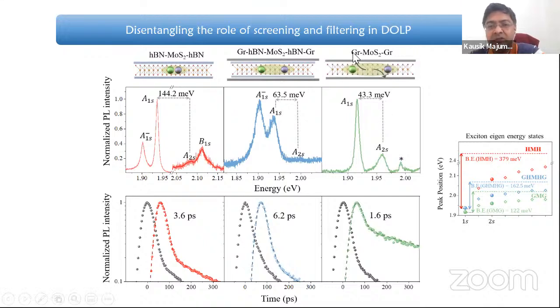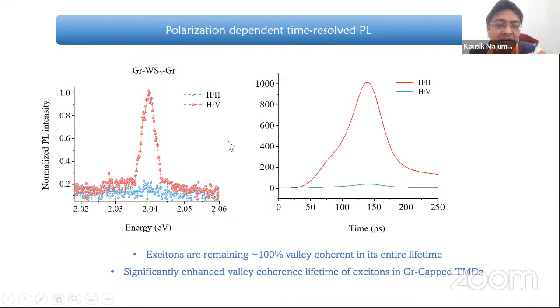And thirdly, in our graphene encapsulated MoS2 stack, we found a very short 2s to 1s separation of about 43 millielectron volts. The corresponding binding energy was about 122 millielectron volts. So you really push the electron and hole apart. However, the lifetime did not increase because there's a strong non-radiative loss directly to graphene. So you're truncating the lifetime, as well as pulling the electron and hole apart, so cutting down the exchange interaction. And that's how we believe that we have achieved this 100% polarization. This is also repeated on a different case, the tungsten sulfide. So graphene encapsulated tungsten sulfide.